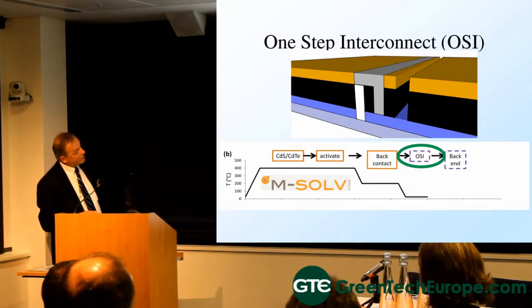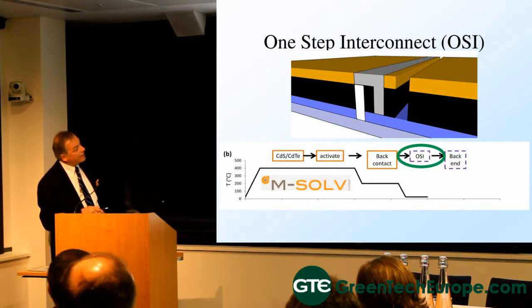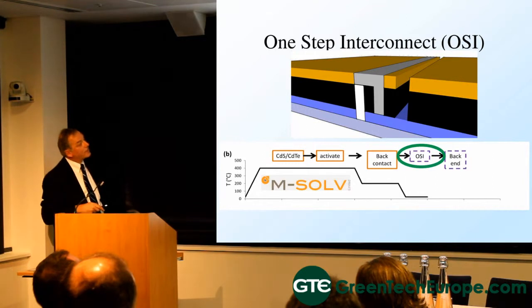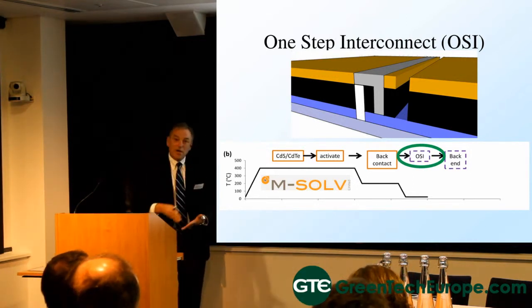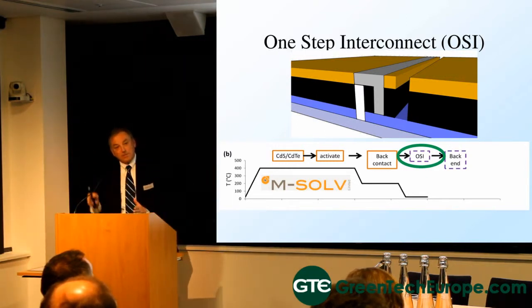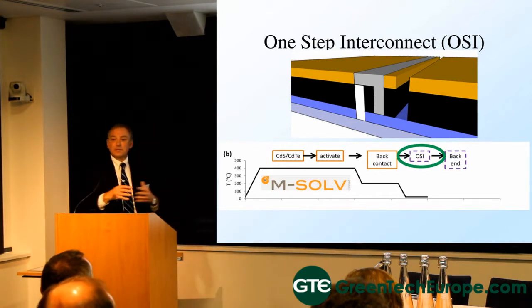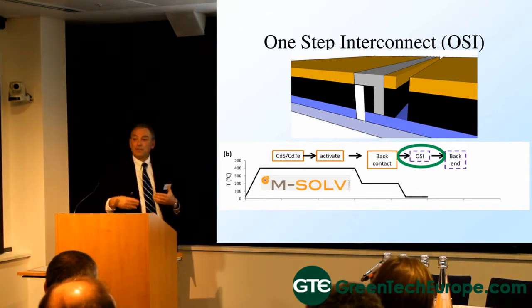this is the top contact, this is a transparent conducting oxide above the glass. You have to isolate cells by ablating down to the glass through the TCO, and then connect the TCO through to the top contact, so that the cells are then connected in series. Conventionally, in the manufacturing process, you scribe the TCO-coated glass down to the glass, then deposit 2 layers, then you take it out of the vacuum system, put it into another scribe machine, scribe down to the TCO, put it back, and then deposit the metal contact. The problem with that is you're in and out of vacuum, you're heating and cooling the module. It leads to huge inefficiencies in the thin film manufacturing process.